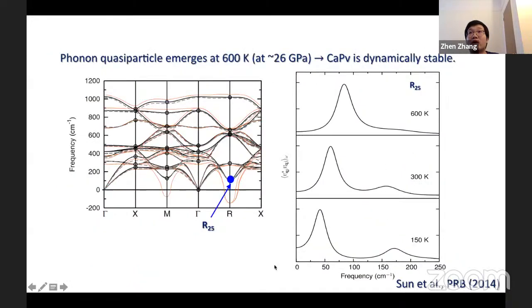Then we use the phonon quasi-particle approach to check the validity of the phonon picture. Here we show the single phonon power spectrum of the soft acoustic R25 mode. It has imaginary phonon frequencies from harmonic phonon calculations. At low temperatures, for example, 300 and 150 Kelvin mentioned above, the power spectrum exhibits non-Lorentzian line shape with double peaks, indicating the breakdown of the phonon picture. However, at 600 Kelvin and the temperatures above, the phonon quasi-particle is well-defined with single peak Lorentzian line shape, which is in line with the dynamical stability of the cubic phase in real space.